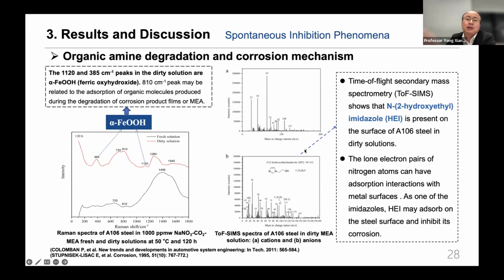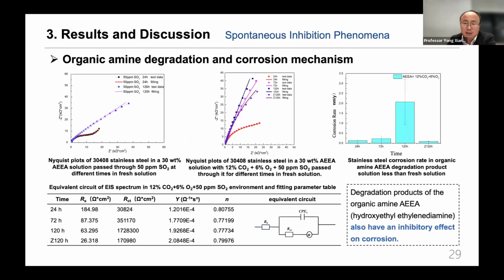That's the reason: the degradation product may work together with MEA, so it reduced the corrosion rate. We also did another, AEEA, which has the same phenomenon. This is the fresh solution. This is the dirty solution. The corrosion rate is also much smaller than the fresh solution.